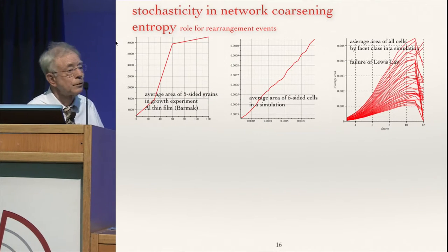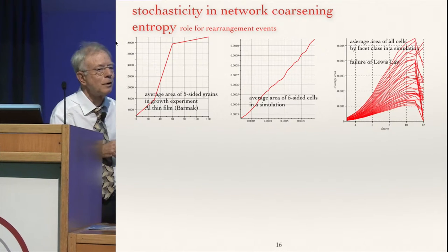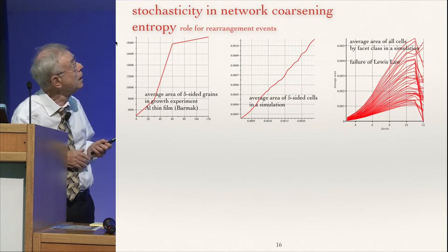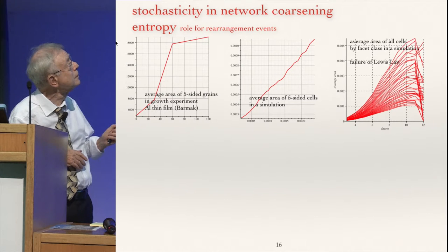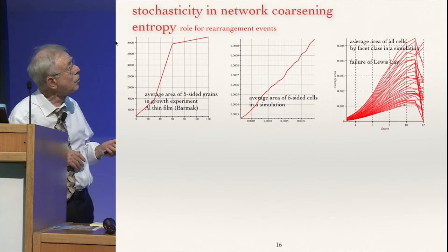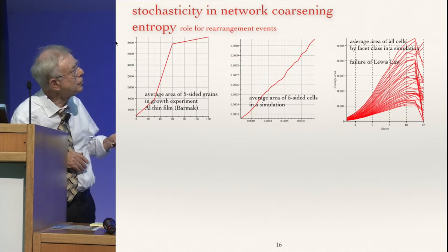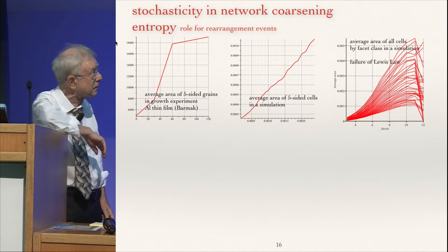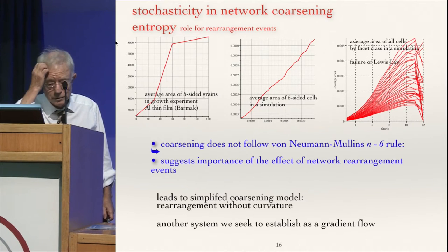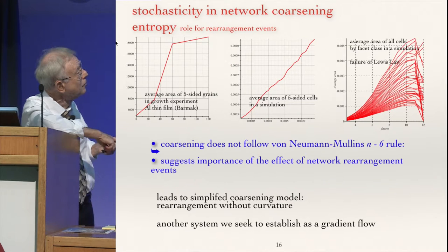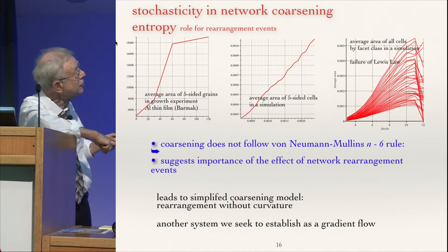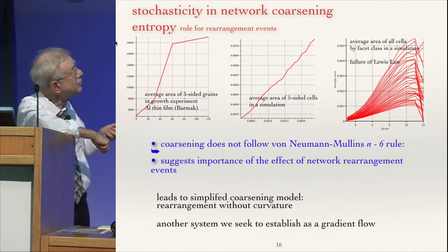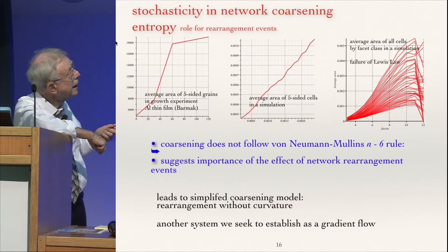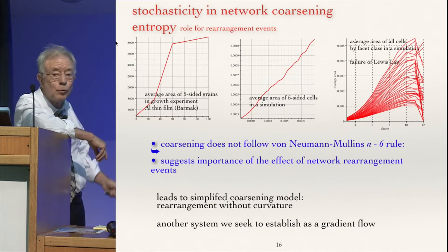Now, just as there was stochasticity in the urn, where you pick something, there is a great deal of stochasticity in this grain growth process, in this coarsening process. Here is the average area of five-sided grains in an aluminum thin film experiment, and here in a simulation. At a given time, you go up and you see the average area for that facet class. However, what we know already from the von Neumann-Mullins law is that five-sided grains should be decreasing. What is happening is that at this time, you are looking at cells which had six sides or seven sides or eight sides a few moments before.